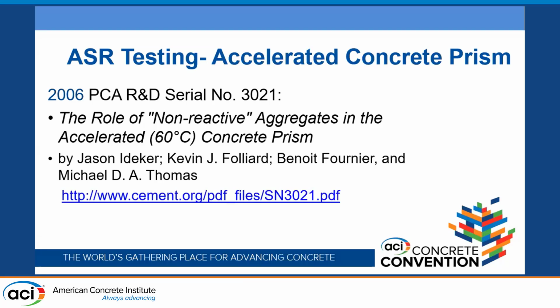And then going on to these higher temperature ranges, there was a report done in 2006 by several of the people that you're going to hear from today on the role of non-reactive aggregates. And so this is the study that Jason's talking about and continued throughout the project. And since Jason just covered it, I won't get into great detail except to just summarize that it's really important that they noted that after initiating the test programs, they found two important observations: that the expansions in the 60 degrees Celsius version were considerably less than those at 38 degrees Celsius, which they wanted to know why at the time.